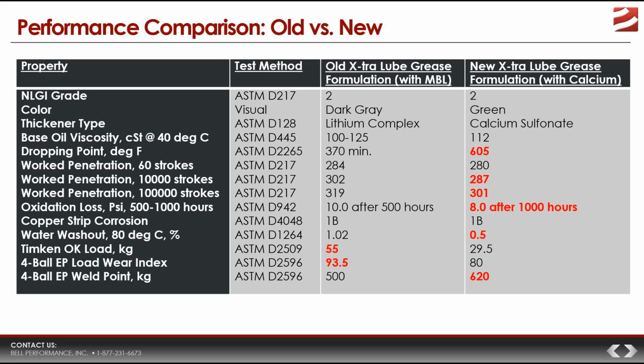The next test is oxidation loss, documented as ASTM D942. It measures how resistant a grease is to oxidation under static conditions. We know that when using grease at higher temperatures, above 200-250 degrees, for every 20 degree Fahrenheit rise above that floor, the oxidation rate of a given grease actually doubles. Many lubricating scenarios have constant temperatures much higher than this.